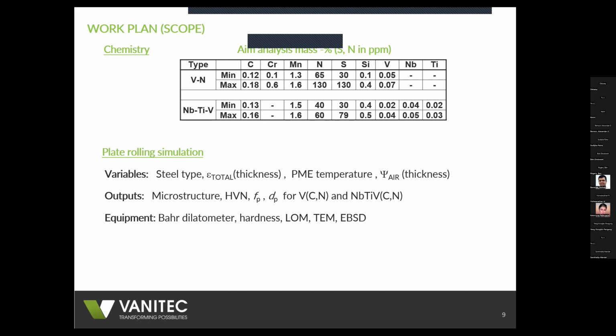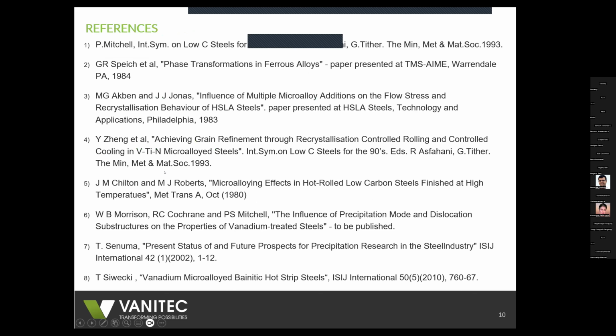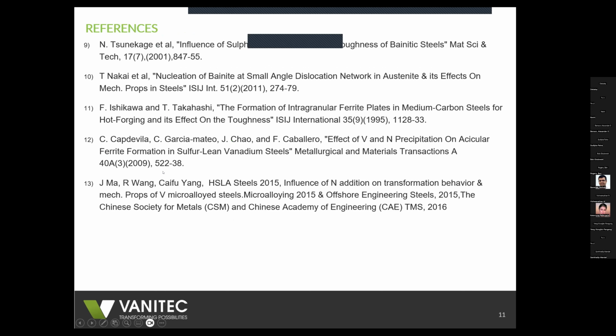Particularly good simulations can be done on thick plate, where the strain is limited. And then we'd use, of course, hardness machine, light optical microscopy, TEM, and EBSD. And then plate rolling trials, we would use the same approach, but include tensile and Charpy tests, of course. Okay, these are the references used in the compilation of this document.